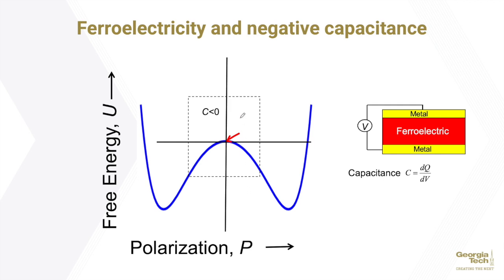The capacitance of a capacitive material is defined as the inverse of the second order derivative of the free energy with respect to the charge or polarization. Now in this energy minima region, this second order derivative is positive, which means that in these two regions the capacitance is positive, but in this barrier region, however, the capacitance is negative. Naturally this region is energetically unfavorable because it is a high energy state. So if we want to put the polarization over here, the polarization will spontaneously roll downhill to one of these positive capacitance states. In other words, this negative capacitance state in a ferroelectric material is unstable.